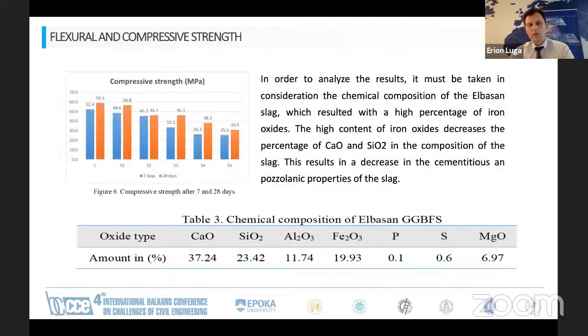Now we have to analyze this part. Why is there such a decrease while increasing the amount of slag? From the results and from the chemical composition, we can see that there is a very high amount of iron oxide in the composition of the slag. So in order to analyze the results, the chemical composition of the slag must be taken into consideration, which showed a high percentage of iron oxide.